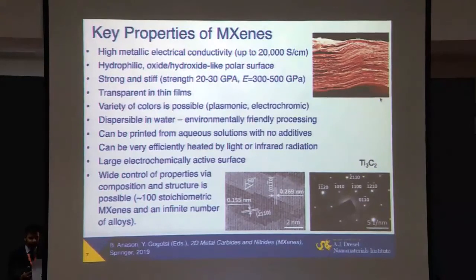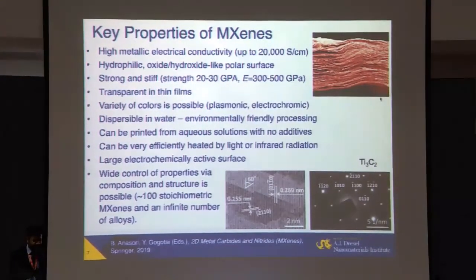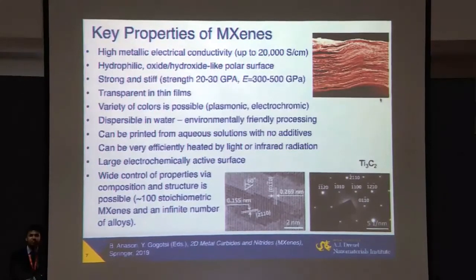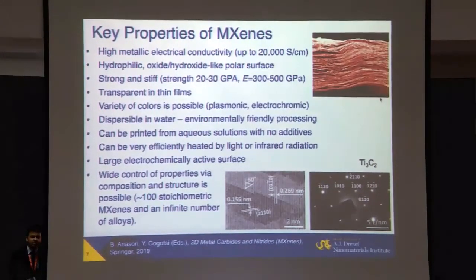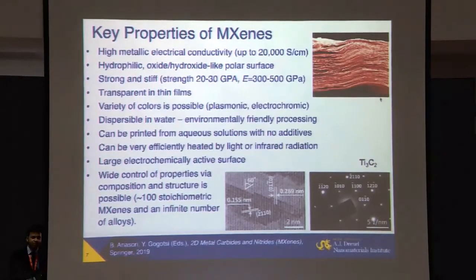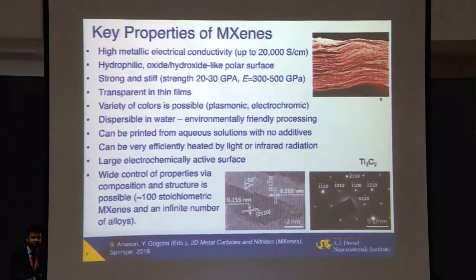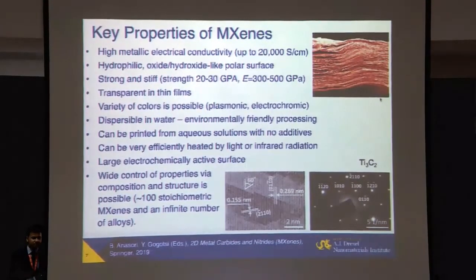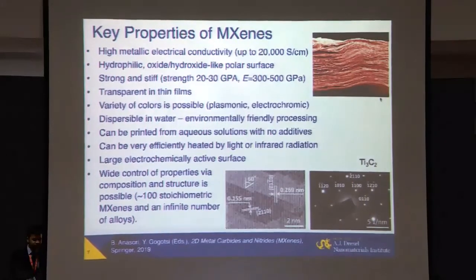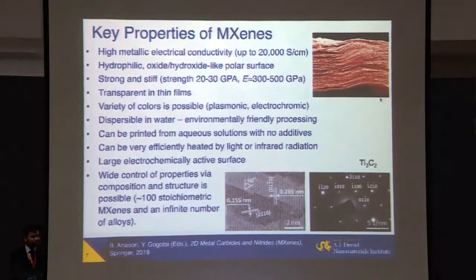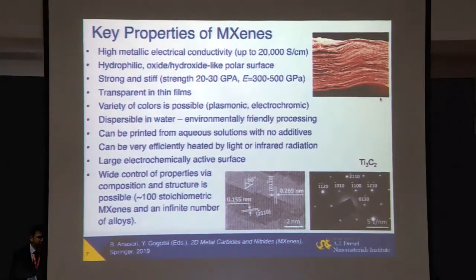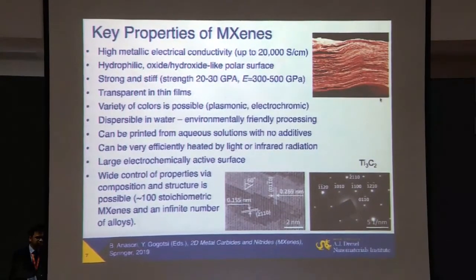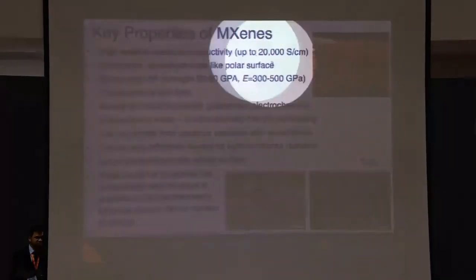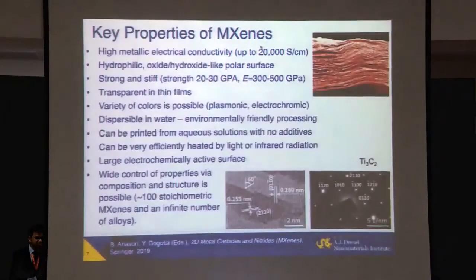People like to say that graphene is a great conductor. Well, it's actually a zero band gap semiconductor with very few carriers, and you have to dope it, create defects, to produce carriers in the material. Those materials have a high density of states at the Fermi level and a high concentration of carriers. As a result, if you don't want a monolayer graphene, but make a film out of graphene, which is what most applications really require, from reduced graphene oxide or mechanically exfoliated graphite, you actually end up with conductivity of about, say, 2,000 Siemens per centimeter. We get up to 20,000 on titanium carbide Ti3C2 MXene right now.